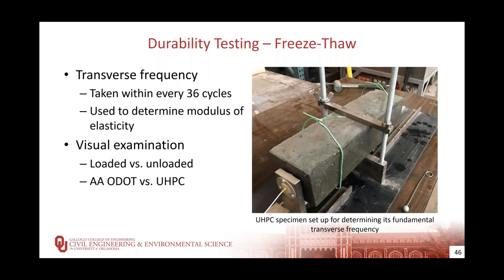Within every 36 cycles, we will remove the specimens and take a reading of their fundamental transverse frequency. This information will help us keep track of any changes to each section's modulus of elasticity. During these recordings, we will also note any physical changes to the specimens.